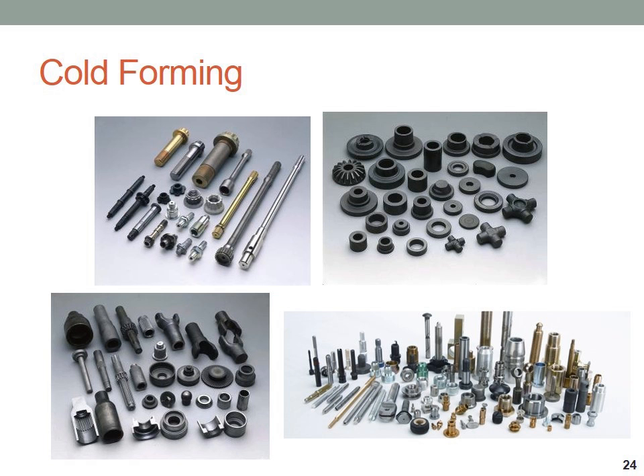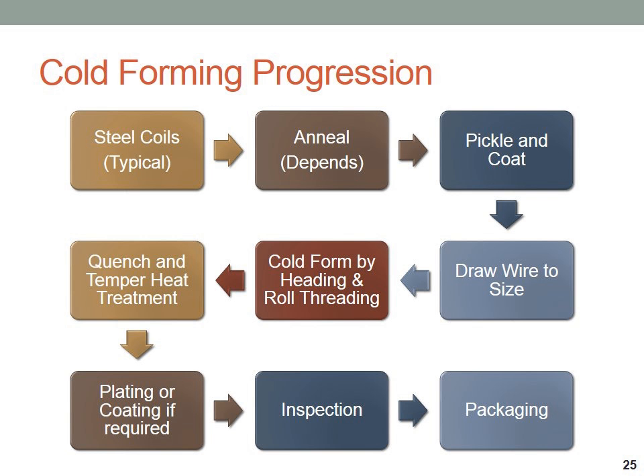And the cold forming process itself, it may have a few tweaks from manufacturer to manufacturer, but generally follows this flow from steel coils to an annealing process, to a pickling or a cleaning and coating. The wire is then drawn down to size, cold formed by heading and typically roll threading. It's then quenched and tempered as a heat treat process, plated or coated as required, inspected, and then packaged.